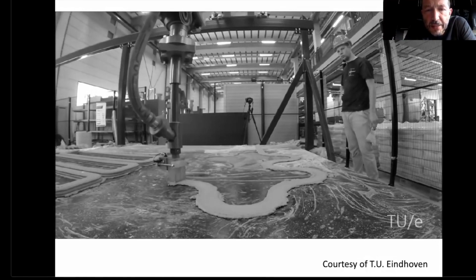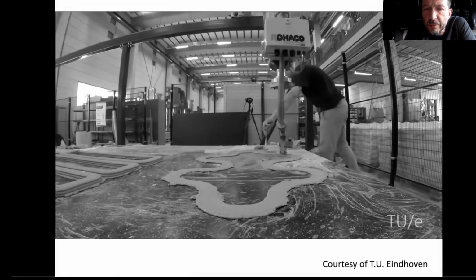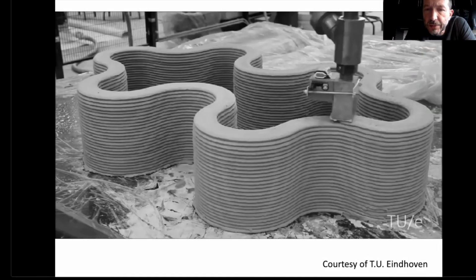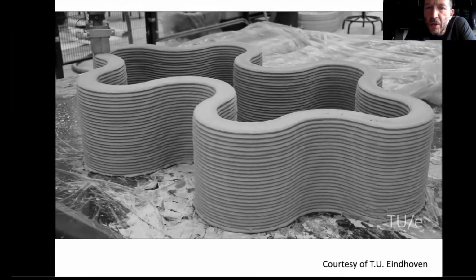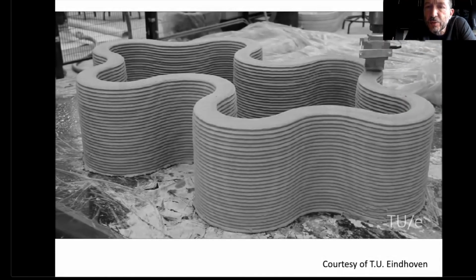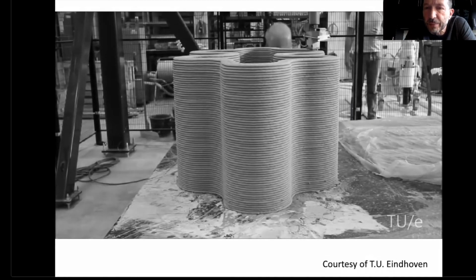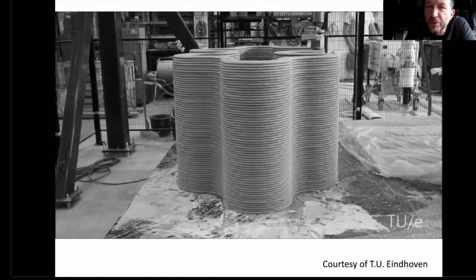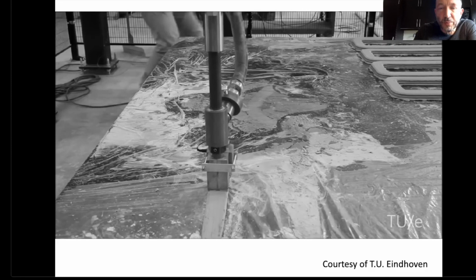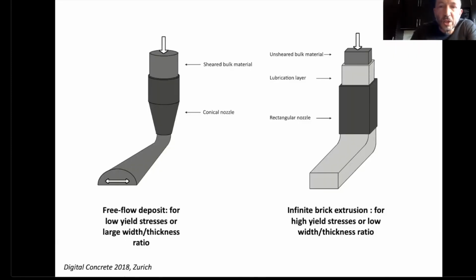And we can see that first we need the material to have a yield stress that is high enough for the layer that is deposited to be stable, to have a controlled shape. But then the stress inside the system is increasing as you print, because you are superimposing layer by layer, and the gravity-induced stress is progressively increasing. So let's first have a look at the yield stress that is required for the layer to be stable.